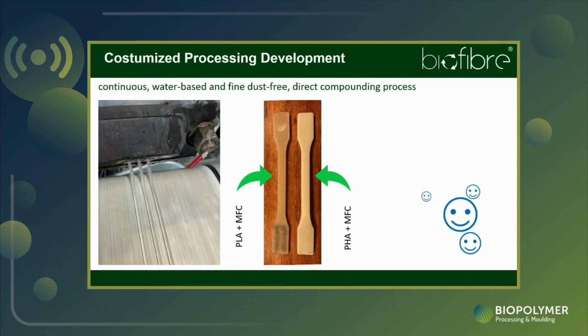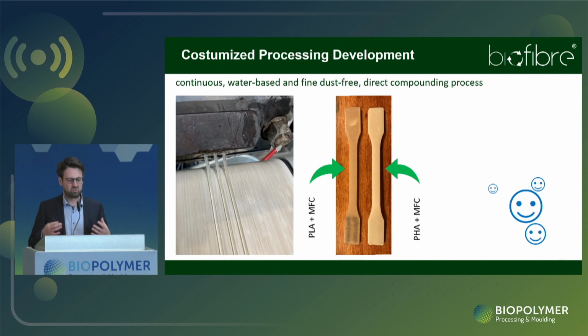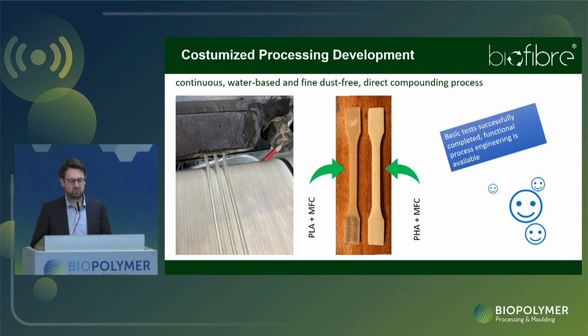What we achieved last year was a continuous water-based and fine dust-free compounding process with a drastically reduced amount of water, which is one of the key aspects. And we tried this with PLA-based materials, but as well with PHA-based materials and PBS-based materials, and it works quite well, and we have an even and fine distribution with really interesting properties. And these basic tests were successfully completed, and the functionality was proven in